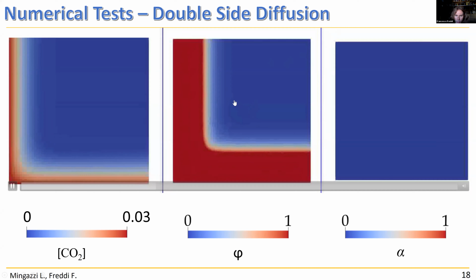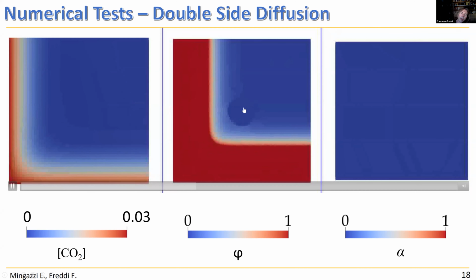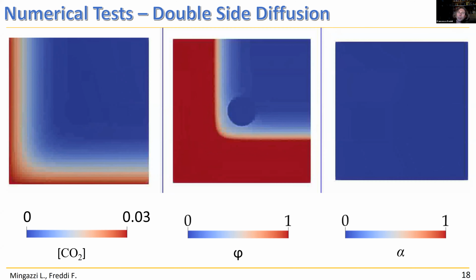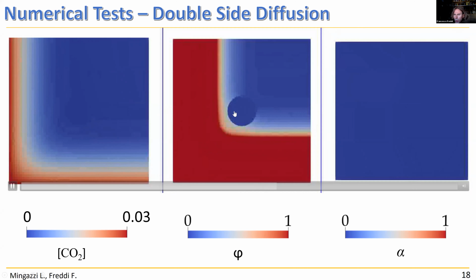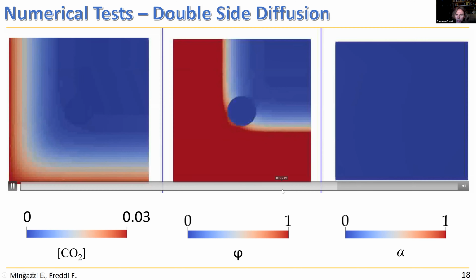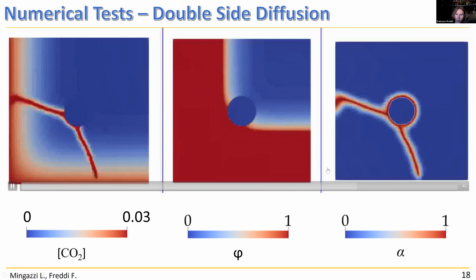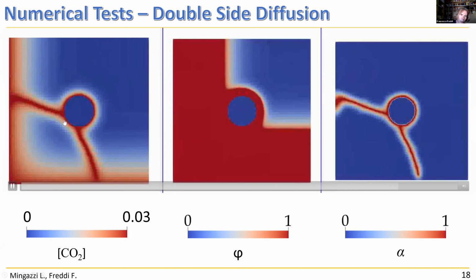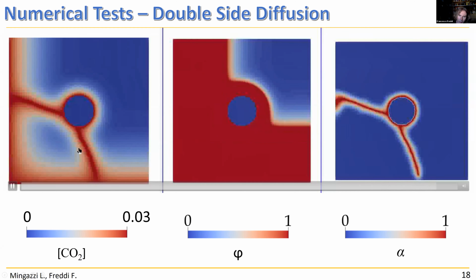You can see here that there's the bar that is not interested by the carbonation, obviously. And as the carbonation front reaches the bar, we will see that a crack initiates and propagates and cuts this corner very rapidly. And at the same time, you get the diffusion within the concrete element that is extremely rapid.